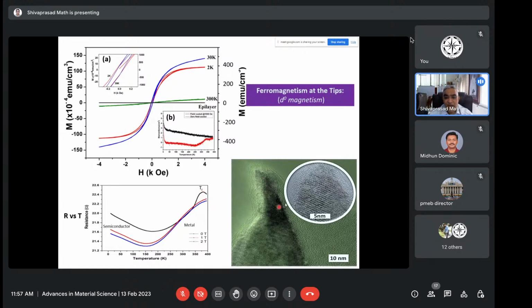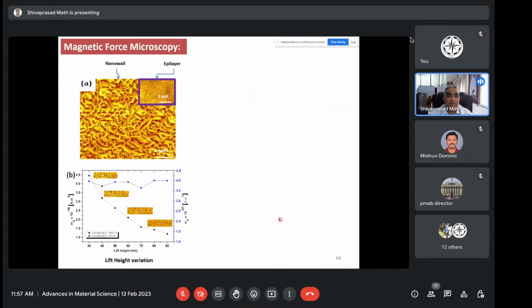So then we looked at where the ferromagnetism is coming from. Then we did some MFM studies, magnetic force microscopy, and we could see magnetism at all the tips of these nanowalls. So why are only the tips ferromagnetic? Of course, you know that MFM was contested. Many people said that this is more of topography. It is very difficult to separate the magnetism and the topography in the MFM measurement. So you have to do it at different heights and show that it still continues. And so it's not a topographic effect, because a topographic effect dies as 1 upon r square, but the magnetic remains linear.